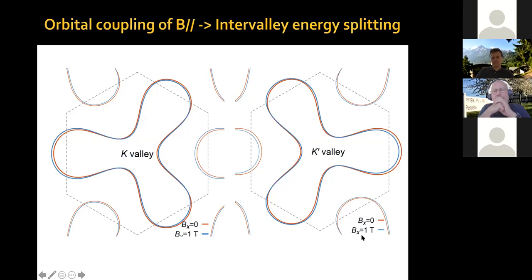But couldn't it be that you have a threefold degeneracy here, but then if one of the three possibilities to nest or to develop a symmetry broken state wins over the others, then the other two options are destroyed? I seem to remember that you have similar cases in transition metal dichalcogenides. Mostly you have a threefold symmetry and you see threefold charge density waves. But I think there are also some cases where you see only a linear charge density wave, although the Fermi surface has a threefold symmetry, because one of the instabilities wins over the other two.